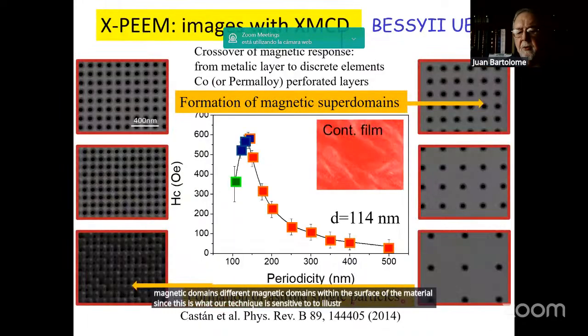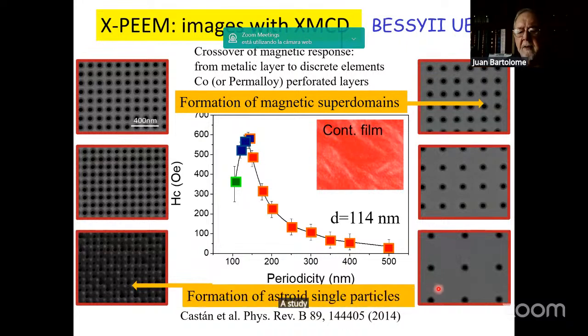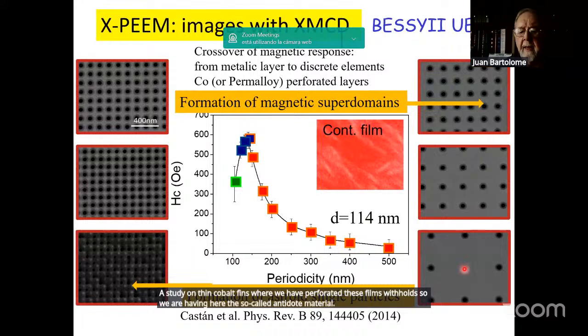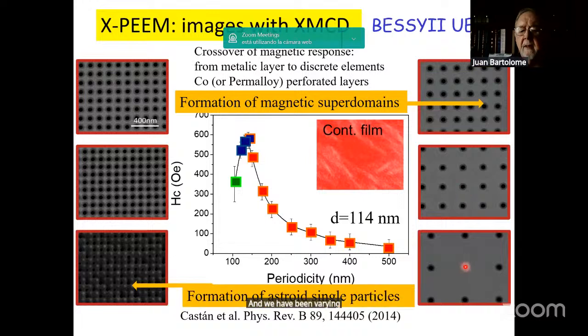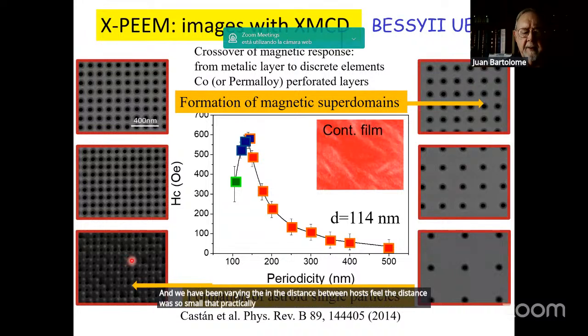And you can see here the result. You can see the presence of magnetic domains, different magnetic domains within the surface of the material. This is what our technique is sensitive to. To illustrate this, I show you here a study on thin cobalt films where we have perforated these films with holes. So we have here the so-called anti-dot material. And we have been varying the distance between holes till the distance was so small that practically the only material that remained was that between the holes.